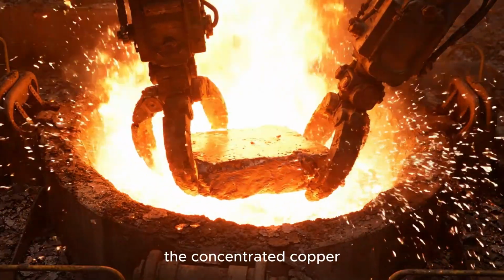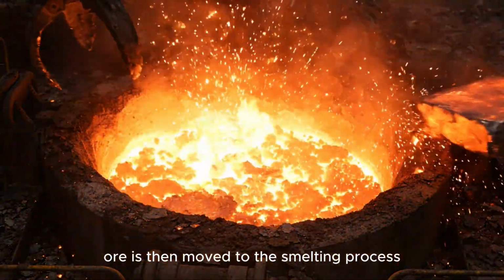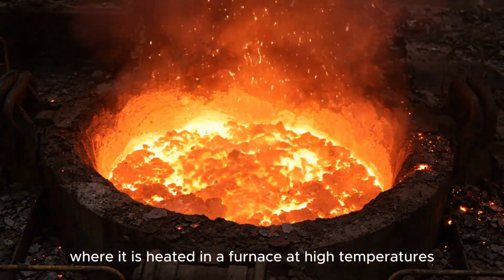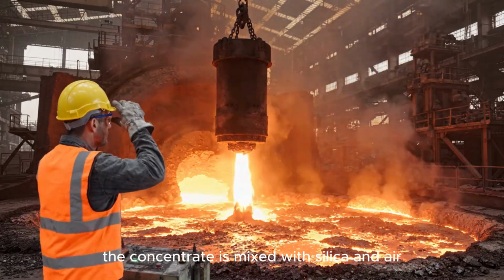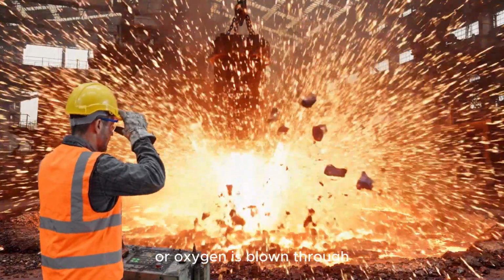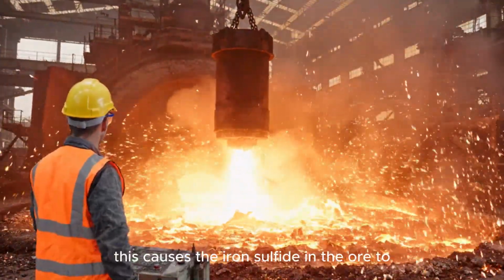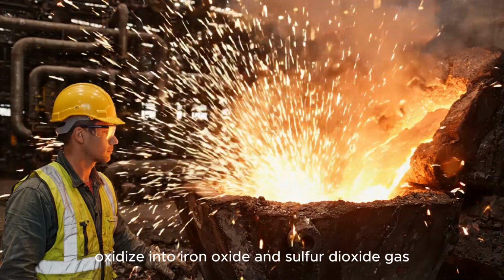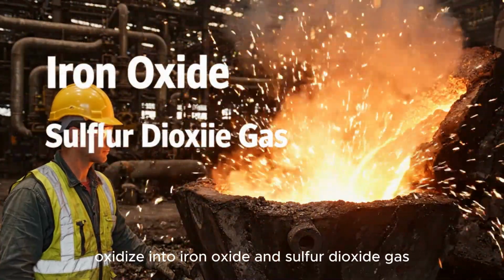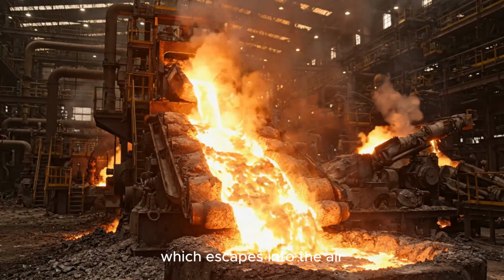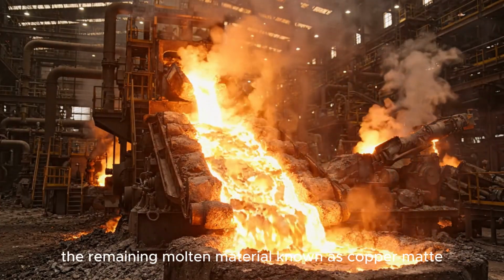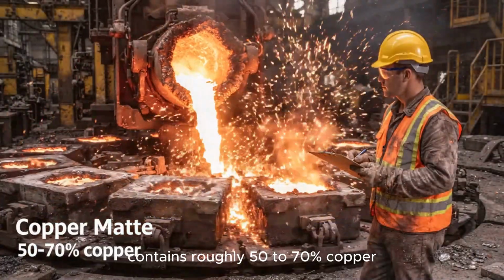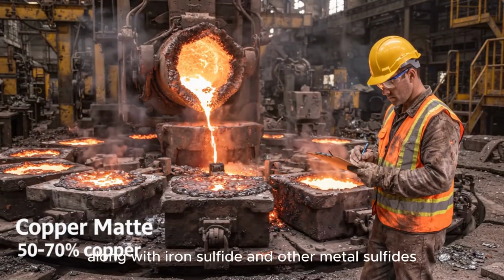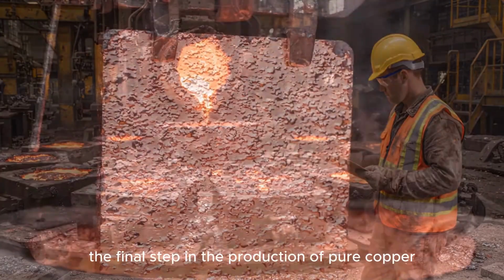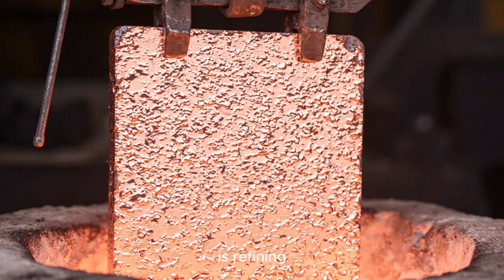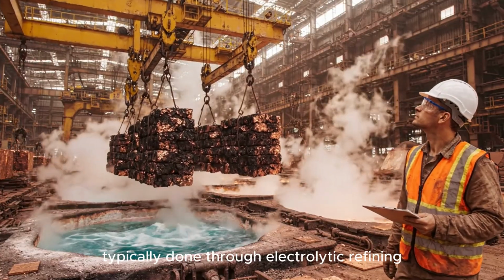The concentrated copper ore is then moved to the smelting process, where it is heated in a furnace at high temperatures. During smelting, the concentrate is mixed with silica, and air or oxygen is blown through. This causes the iron sulfide in the ore to oxidize into iron oxide and sulfur dioxide gas, which escapes into the air. The remaining molten material, known as copper matte, contains roughly 50 to 70% copper, along with iron sulfide and other metal sulfides. The final step in the production of pure copper is refining, typically done through electrolytic refining.